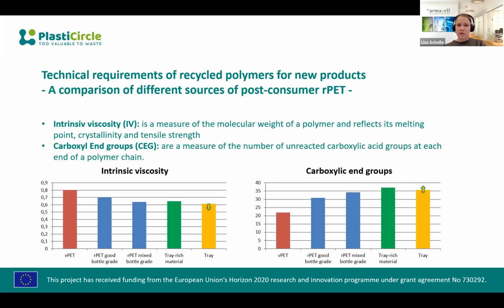And you can see that the quality of the tray material is worse than that of the other materials. This poses a challenge for the processing. What is important to mention here is that the tray provided by the project is flakes, while all other materials are granules. So the values for the granulated tray material could be even lower for IV and even higher for CEG.